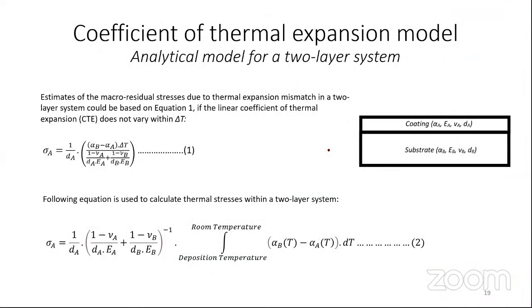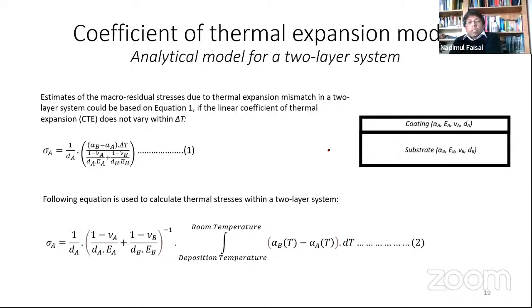Now, if you're looking into a two-layer system, analytical model, the coefficient of thermal expansion model, it is mainly to do with the coefficient of thermal expansion. And you assume that those properties are constant. You assume it's got one elastic modulus, Poisson ratio, and you use this model to calculate, to have an assessment of what could be the likely strain or stress. But it is very far off from the reality.